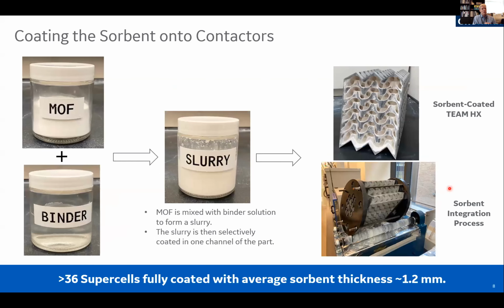So how do we go about coating the sorbent onto the contactors? I showed you the MOF material. We have binder formulations. Think about it like a glue. And we've actually used Elmer's glue before. It works, not nearly as well as some of the proprietary formulations that we've developed. You convert that into a slurry and eventually coat this onto a sorbent-coated heat exchanger as I've shown here.